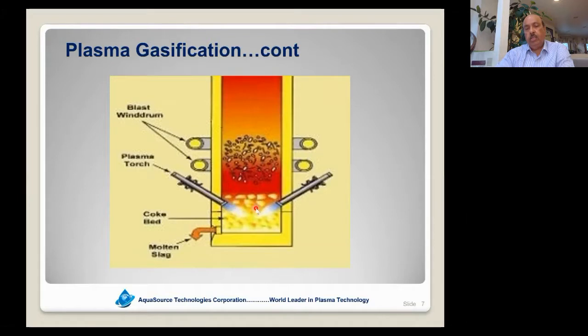And this is where the destruction and gasification take place, on a medium which might be coke, foundry coke, coal, anthracite coal. And this is the waste that is put inside this regular furnace for gasification. So I want to impress on you that although we are using a very high-tech device here to generate the plasma conditions and therefore very high temperatures, these temperatures are contained by proprietary nozzles in the center part of the reactor.